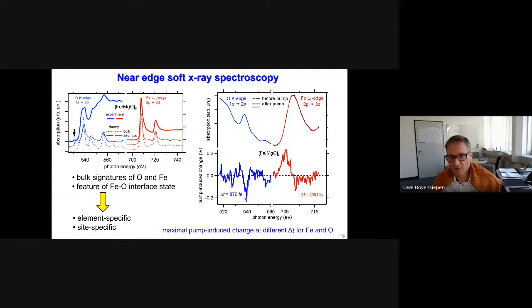For example, here we see a drop in the intensity maximum at the oxygen K edge absorption. Here, this is maybe not so clear whether this is noise or a signal. At the iron L3 edge, we see essentially a red shift of this pump-induced change. So this indicates that we see a shift to lower energy and maybe some smaller intensity redistribution. So intensity drop. So what I would like to emphasize is that the time where we see these maximum changes differ by about 3 times.